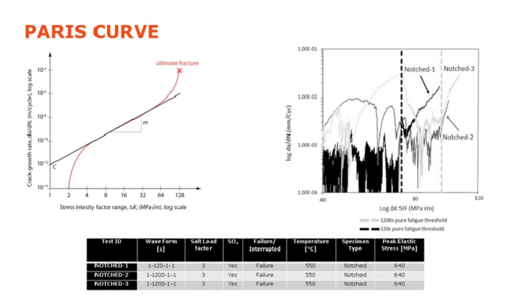And again, we can hypothesize that that could be due to a couple of reasons. There's crack closure, which can occur. That's where your corrosion product actually wedges open your crack, effectively reducing your delta K, your stress intensity factor range, because there's less crack opening and closure occurring. Or there's also crack tip blunting effects, which can also happen. But this relationship of corrosion suppressing fatigue growth is perhaps slightly counterintuitive. It's important to highlight the fact that suppressing fatigue growth is certainly not suppressing the corrosion or stress corrosion cracking driven propagation going on earlier.